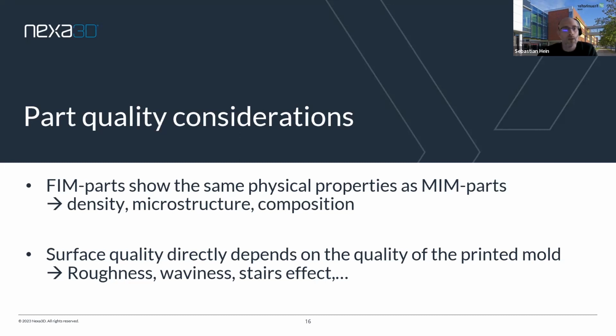So very interesting still. And from a metal side, it's the same. So density, microstructure, the composition. So as Lasse also said, we don't have any residues from the mold. So after sintering, the microstructure and the density are there, same as MIM parts. So it's just the other properties like the surface quality that directly depends here on the printed mold and that you have to take into account. Of course, there are some surfaces also from your printed part that are better than others.